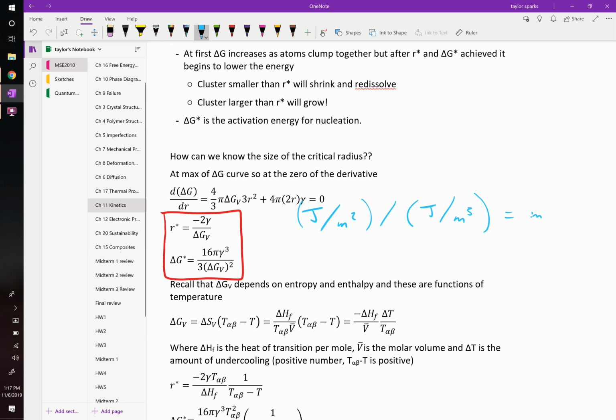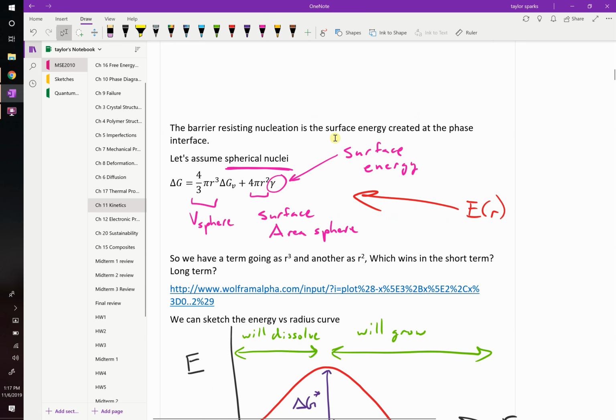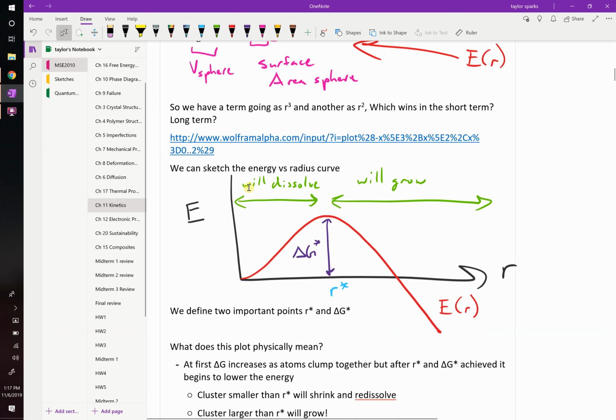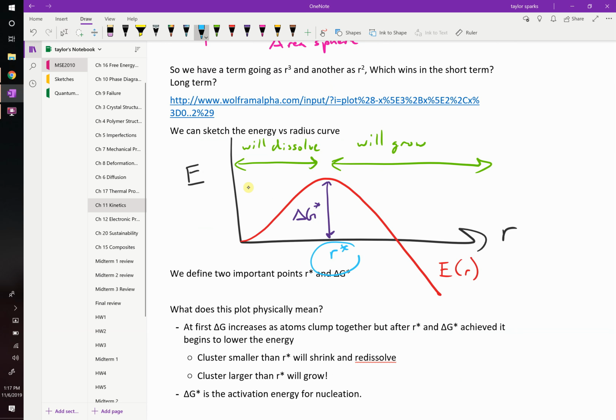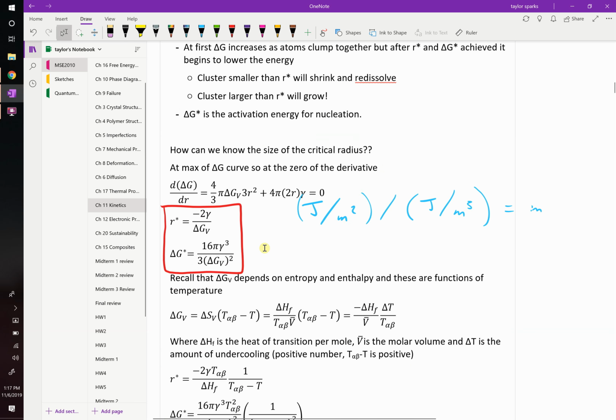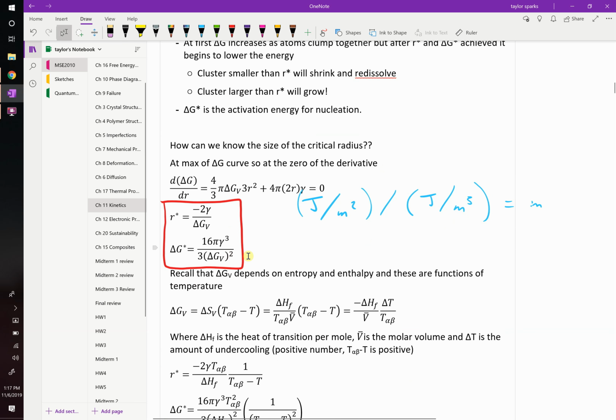Now, you can do the exact same thing. Once you've got r star, we figured out what it is, we can go back up to our energy as a function of our expression, this guy. We can plug r star into that expression, and now we have an expression for delta G star. In other words, by plugging this value of r star into this expression, we solve for this value right there, which is delta G star. We're just going to plug it back in. When we do that, you get this expression: 16 pi, the surface energy cubed, divided by 3 times the quantity of your change in Gibbs free energy on a volumetric basis squared.